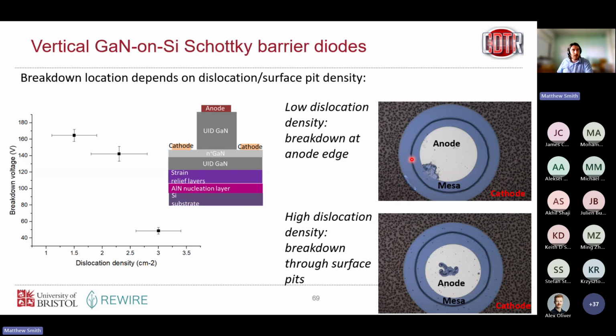So for those low dislocation density samples, we find that the devices are breaking down at the edge, similar to what we saw in our GaN on GaN devices, suggesting we're limited by edge termination here. For these high dislocation density samples, actually they break down not at the edge, but the breakdown seems to be aligned with these pits that we see in the surface. So probably these pits are acting as current paths, and we're seeing maybe some thermal effects here where the device is breaking down early.